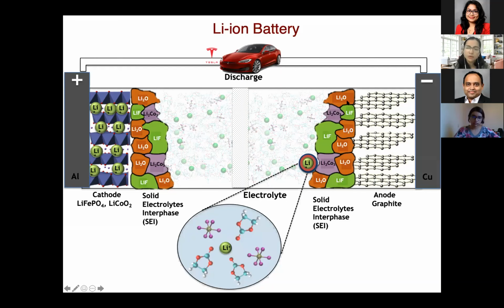The second thing I would like you to remember here is the formation of the solid electrolyte interface, which we form due to decomposition of the electrolyte species at the interface. In lithium-ion batteries, this SEI layer acts as a protective layer. It protects the anode, but at the same time, it allows conduction of lithium ions, okay?